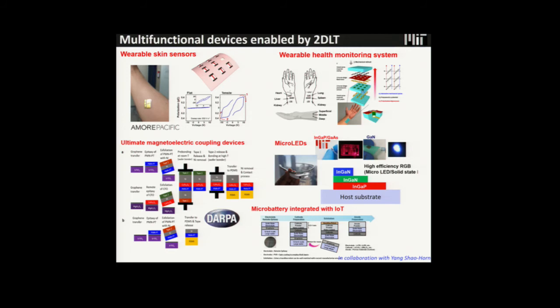How can 2D-LT impact it? So far, micro LED has a processing problem because you really need RGB with high quantum efficiency on one substrate, in one location. But for example, the highest quantum efficiency material for blue is gallium nitride, a III-nitride. But the highest quantum efficiency material for red is III-V. So III-V and III-nitride cannot go onto the same substrate because their lattices are totally different.